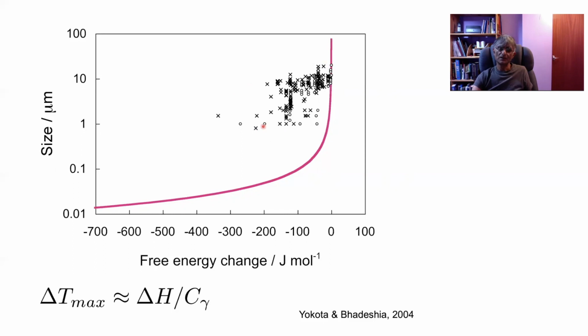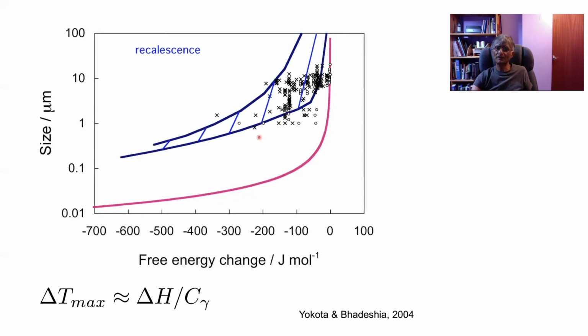Okay? Now, the reason for this is that when we undercool, the enthalpy change of transformation also increases. And furthermore, the rates of reactions can sometimes increase. So the heat of transformation basically removes the undercooling. It heats up the steel. And when we take account of that, it isn't very likely that we can produce nanostructured steels using the hot deformation method.